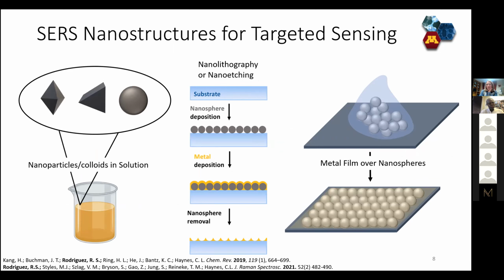You put in a salt like tetrachloroaurate with a reducing agent, and if you have the right reaction conditions and surfactants, you can make some very nice nanoscale colloidal solution particles. That's very useful if you want to do detection in a liquid phase. Often people want to do detection on a solid substrate instead. And so in the middle of the slide, you can see one way people might make a nanostructured substrate. In this case, put down some polymer nanospheres, some beads, and then deposit metal on top and remove the mask, and whatever reached the surface is left there.